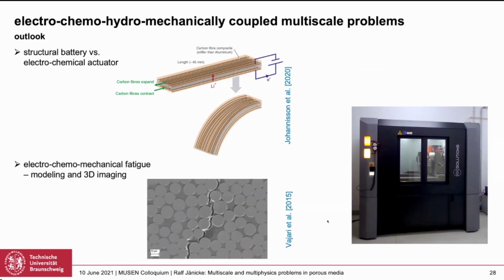Something we would like to continue in future is not only the application as a battery, but it can also be used as an actuator. And this is also quite a fancy application. I like it a lot because the idea is if the lithium ions are intercalating the carbon fibers, it happens that they expand. They expand by 3 to 5% in thickness direction, and also 1-2% in longitudinal direction. And if this is oriented in a right way, this leads to a bending of such a composite. And this, of course, could be used as an actuator.